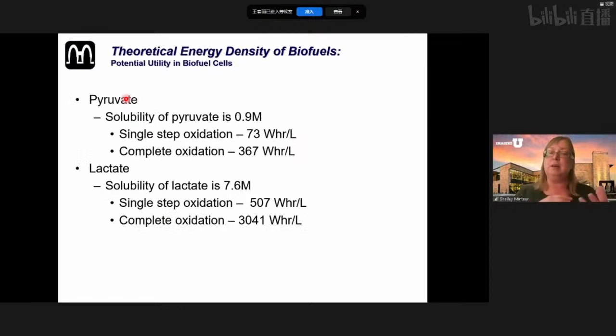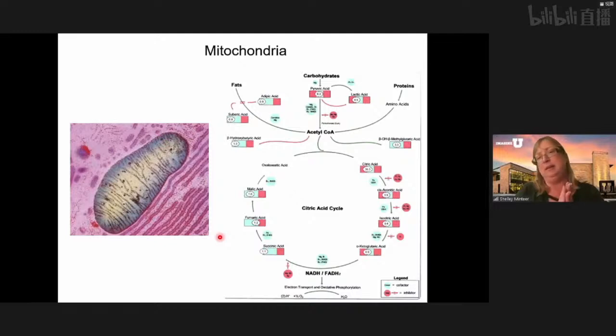Some things to think about when you're thinking about biofuel cells is that we oftentimes talk about energy density or specific energy. And in the case of a biological fuel cell, it's not just the energy density of the fuel. It's not just how many electrons you can get out of the fuel, but it's also the solubility of the fuel because these have to operate in an aqueous environment. So if we look at the two examples I just showed you, pyruvate and lactate, pyruvate's not very soluble. It's only soluble to about 1 molar. And so if you look at theoretical energy densities, even if you do complete oxidation, they're still pretty low. Whereas if you look at lactate, lactate's extremely soluble and you can get really high energy densities from completely oxidizing it. So the moral of the story is you need complete oxidation, but you also need to have high solubility to be able to make energy conversion devices that are ideal.